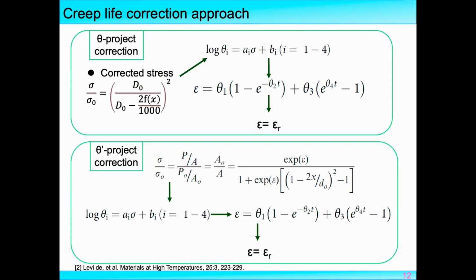We can calculate the creep strain. When the creep strain becomes the rupture strain, we think creep rupture occurred and the corresponding life is the corrected life. Method 4 is also similar to method 3. The only difference is that this method considers that the real stress was affected not only by the oxidation but also by the creep strain. So we use this equation to correct the real stress and then substitute it into the theta projection method, and the other processes are the same as the upper one.